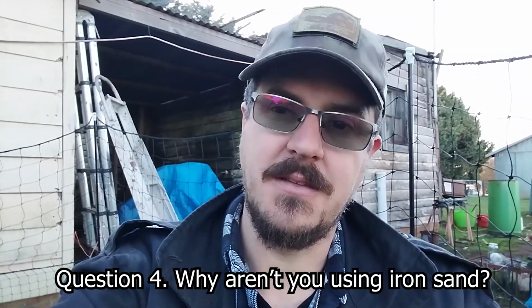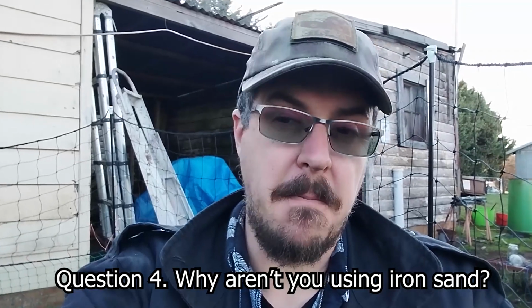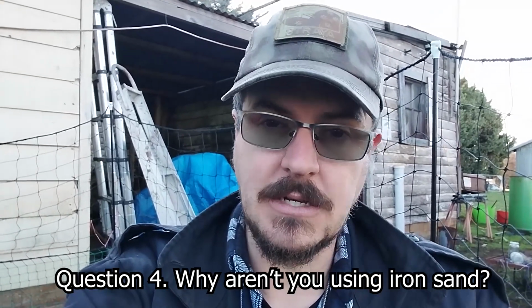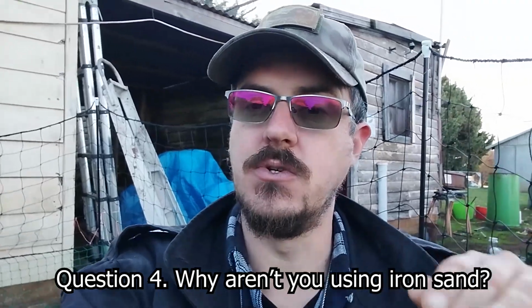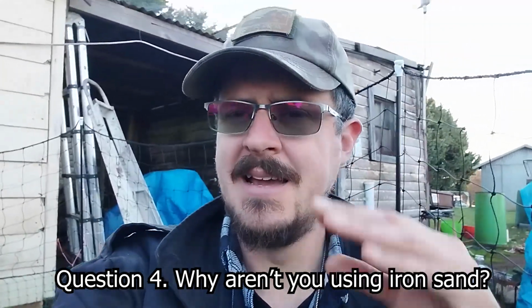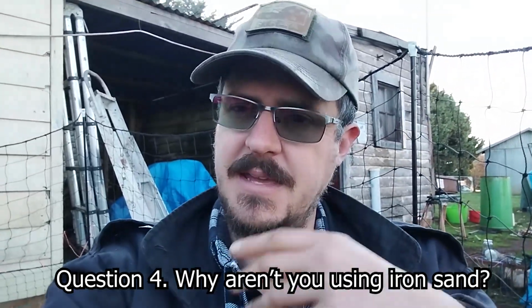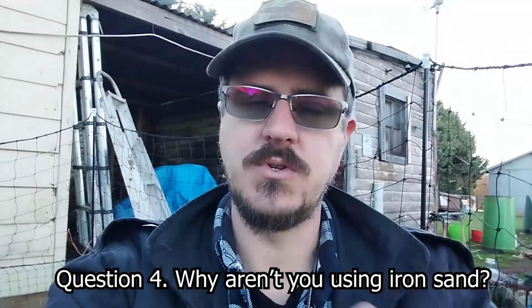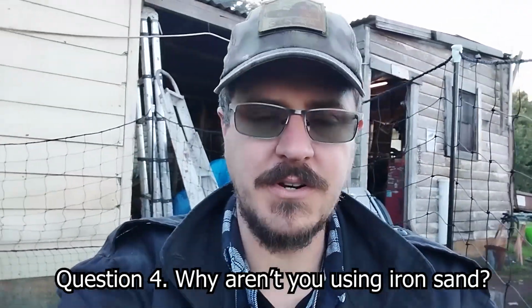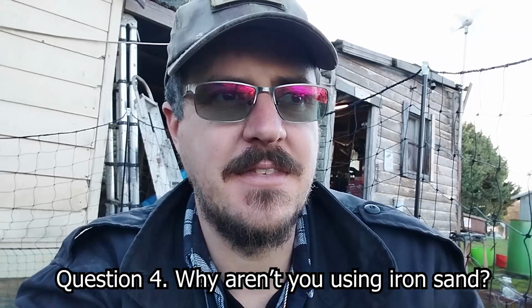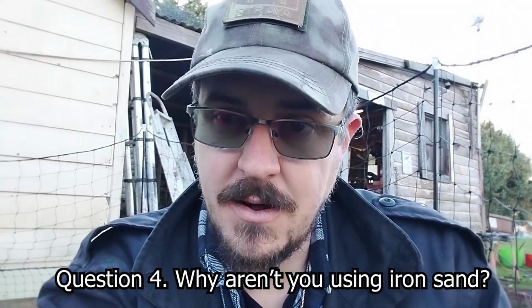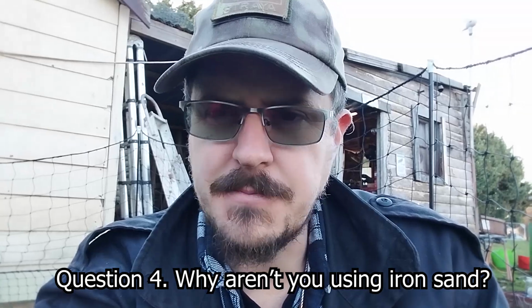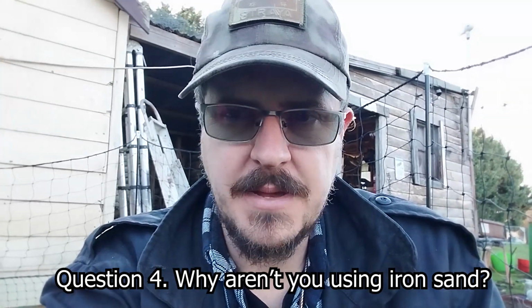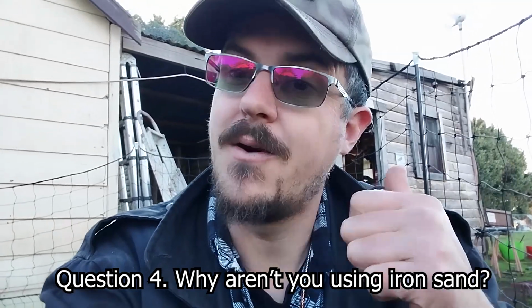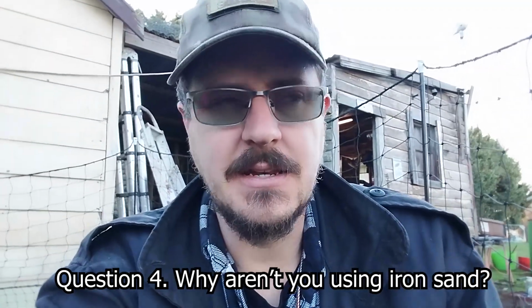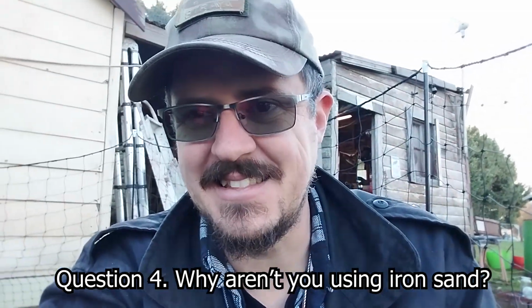Whereas the Japanese tatara method makes a sort of an iron-rich slag mix at the bottom, which is then sorted into various different carbon contents, which are used for the different parts of the sword. And those pieces are sort of flattened down and stacked up by being coated in straw and clay and forge welded together. It's a beautiful process to watch, but it's not the only way to do it. And I think the exposure to tatara as the main exposure for iron sand being used has led to a lot of people thinking that if you are building a bloomery like we're doing, the way to charge iron sand into it is to pour the iron sand in the top.